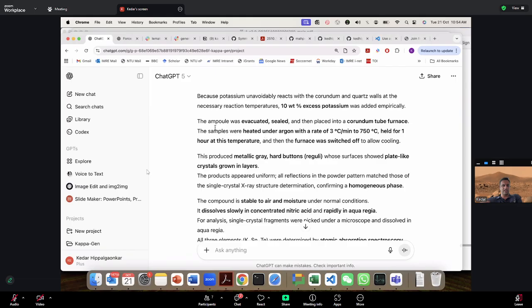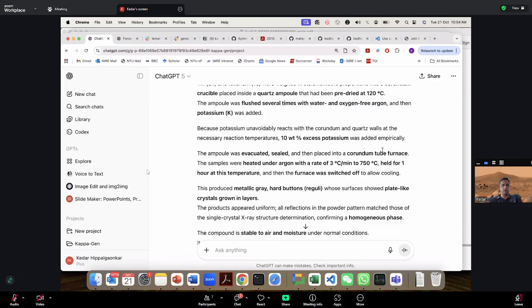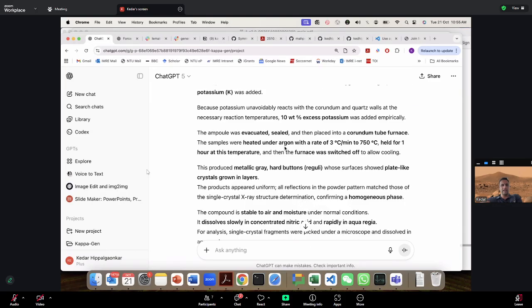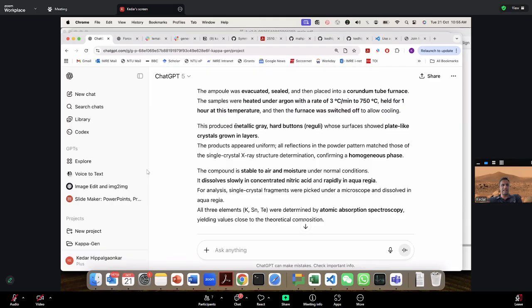Okay, so let's read this. Yes. The ampule was evacuated, sealed, and then placed in a tube furnace, which is alumina. Then heated under argon to 750, held for 1 hour, and switched off. It produces metallic gray plate-like crystals.